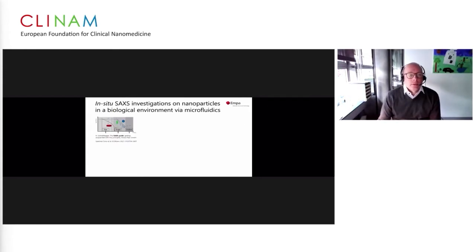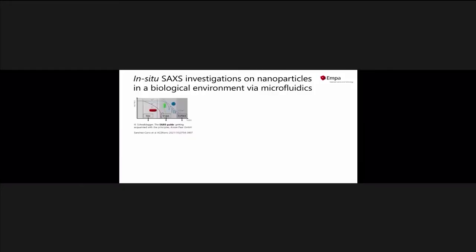We reached that by using small angle X-ray analysis, which is a wonderful technique allowing us to analyze particles, in particular very small particles, in a label-free, non-destructive way. And we can learn from the scattered signal about the size, the shape, the surface, and also to a certain extent the interaction.